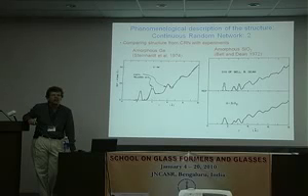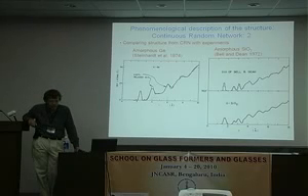Okay, yes? Just a comment. They did these models, right? I think they took a Gaussian distribution of bond angles around some peaks. Yes. And they found that within a few, up to 10%, you would completely destroy the order. The second point is they did a tight-binding approximation with electron hopping on it and got this, at that time, very surprising. You got sharp band gaps. So that implies that the sharpness of the band gap is largely determined by the short-range coordination plus the continuity. Okay. Thank you very much for this comment. Okay. Very nice. Okay. Other questions?